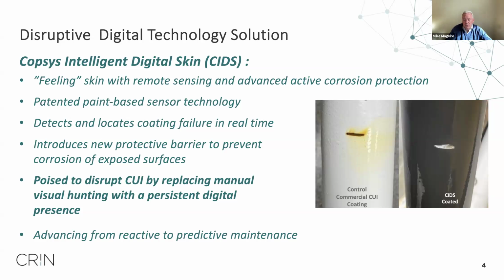Over the subsequent weeks and months of this experiment, you could see the one on the left got progressively more deteriorated and not so pretty to look at. And the one on the right stayed nice and pristine, and there was no evidence of corrosion after weeks and months.